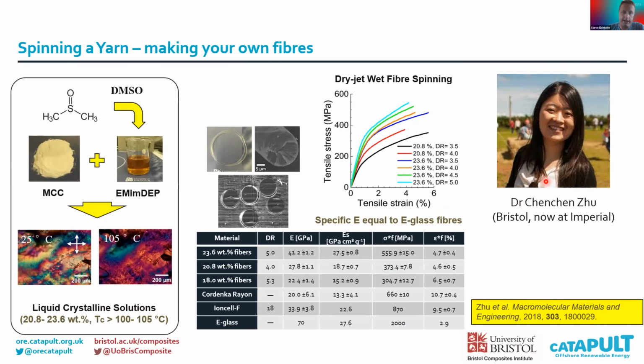We were able to make fibers using DMSO as a co-solvent, and we were able to get some really impressive properties. Stiffnesses of over 40 gigapascals and a strength of just over half a gigapascal. And these fibers really are at the top end of what we call regenerated cellulose fibers, and they could be really useful for making proper structural composites.